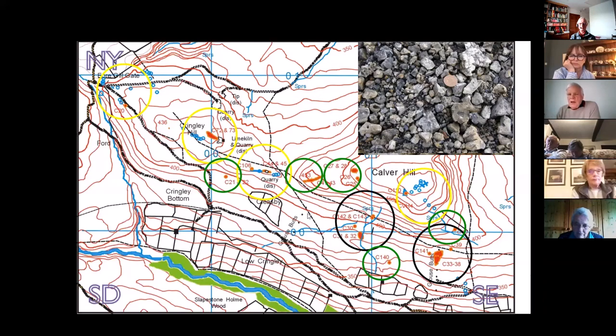You've then got a change in what is happening, and the ore is obviously less well dressed because there's more non-metals in the slag, and you get this more industrialized type of smelting going on. And you'll notice it's lower down the hill. It's still in an exposed position, but it's further down the hill and more remote from the mine. And then finally, these huge sites here, which are both dated in the 1400s, look where there has been a real industry going on here. These slags with about 30% of lead in them have been brought in, maybe from smelting areas further afield, nearer the mines, the big mines up here at Old Gang and Surrender and the like. And you've got some form of industrial process taking place.